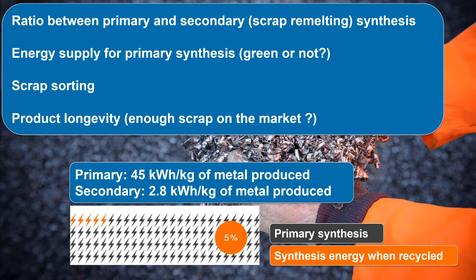Since aluminium alloys are highly sensitive to composition changes, aluminium scrap sorting is one of the most essential tasks in secondary synthesis. Mixing different aluminium alloys can lead to the formation of large and blocky intermetallic particles that form during solidification and make the material brittle and susceptible to failure. Another important aspect in the context of secondary synthesis is the limited availability of certain high-quality scraps on the one hand, and some less desired scrap types in the recycling loop, such as certain cast alloys, on the other hand.